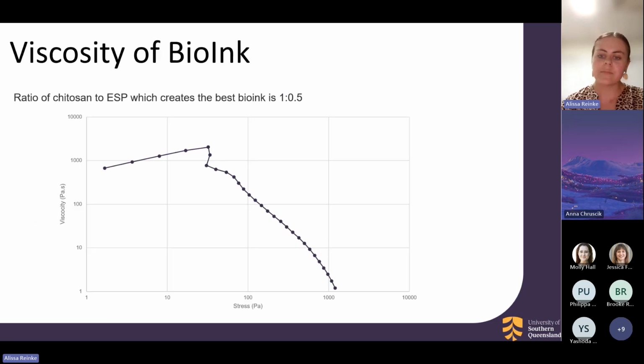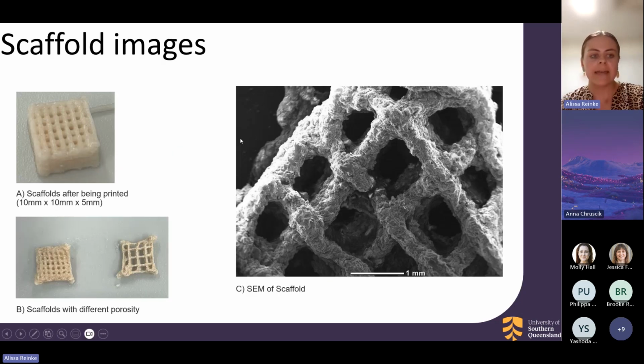So testing the viscosity of the bio ink, that was a lot of trial and error, looking at the different ratios between chitosan and the eggshell particles, to something that the printer was strong enough to print, but also something that held its shape long enough to go through the drying process to then become hard. So the ratio that we found is the most useful is 1 to about 0.5 of chitosan to eggshell protein. And when it is finished being printed, it looks like this.